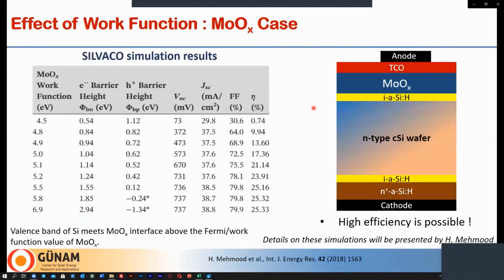Well, of course, here for molybdenum oxide, the work function is a critical parameter. So if you have a very high work function in connection with silicon, accumulation of holes is observed. So these parameters are critical, and the work function usually depends on the material properties. So in order to further understand the effect of this work function on the device properties, we carried out some device simulation using SILVACO for this structure here.